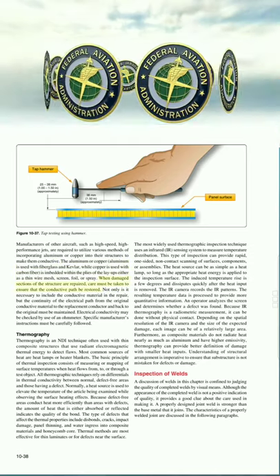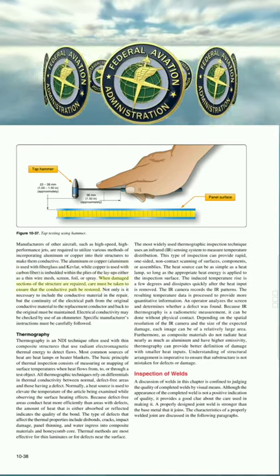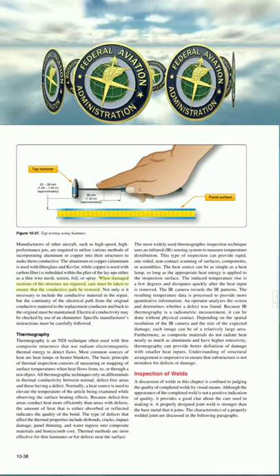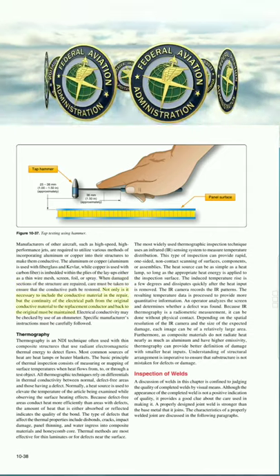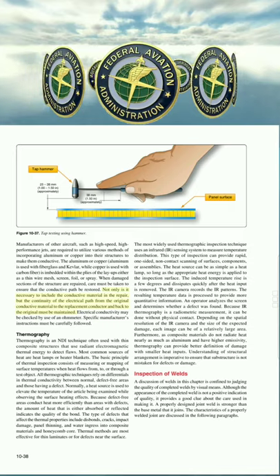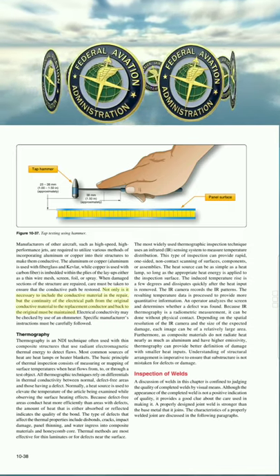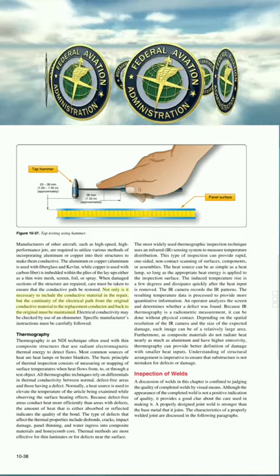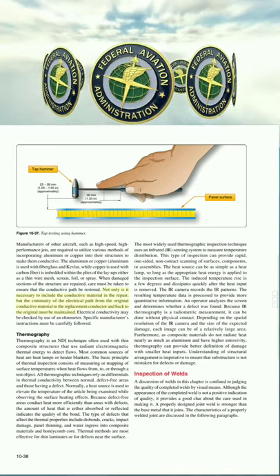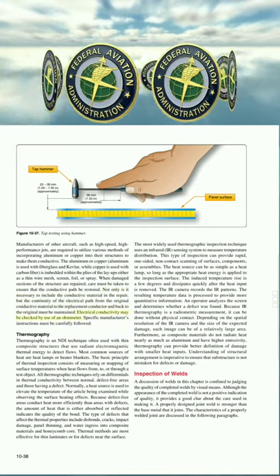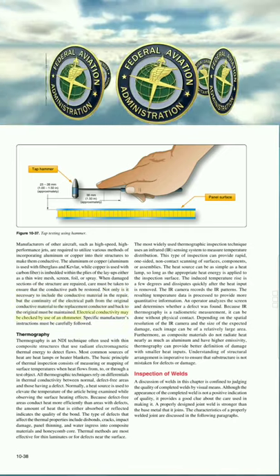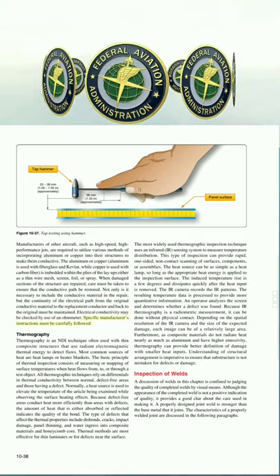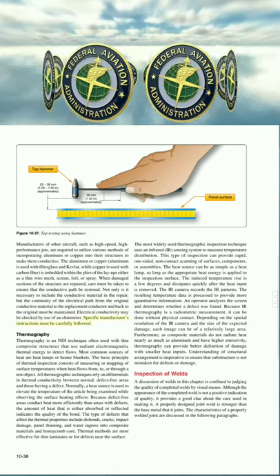When damaged sections of the structure are repaired, care must be taken to ensure that the conductive path is restored. Not only is it necessary to include the conductive material in the repair, but the continuity of the electrical path from the original conductive material to the replacement conductor and back to the original must be maintained. Electrical conductivity may be checked by use of an ohmmeter. Specific manufacturer's instructions must be carefully followed.